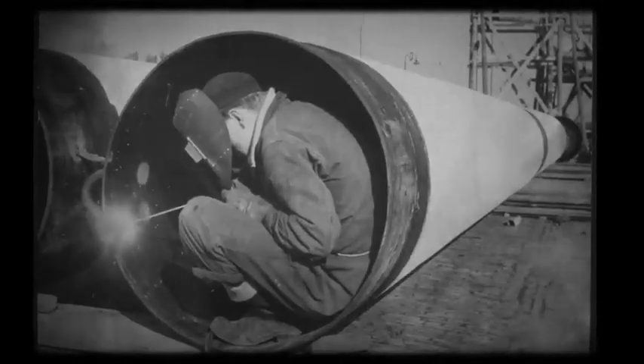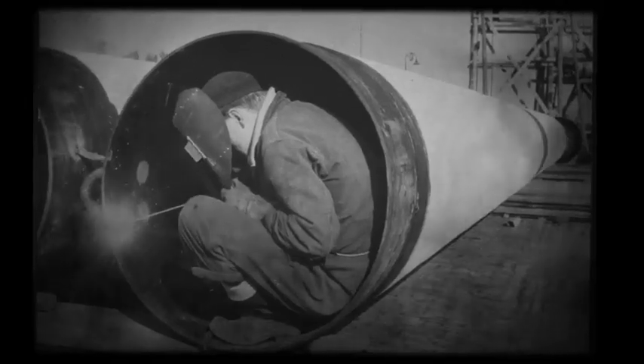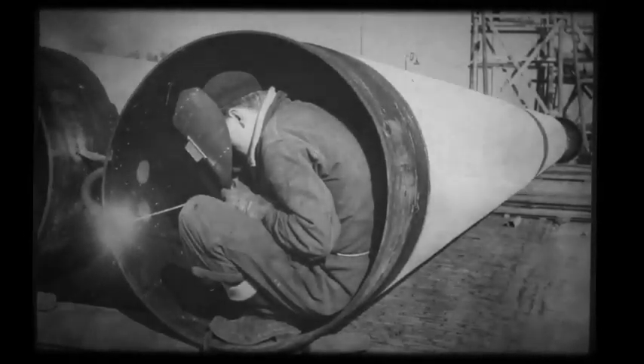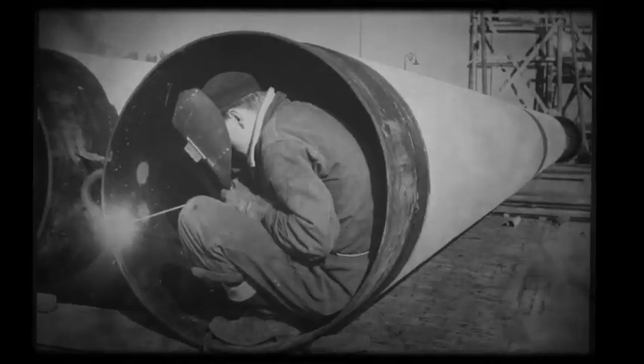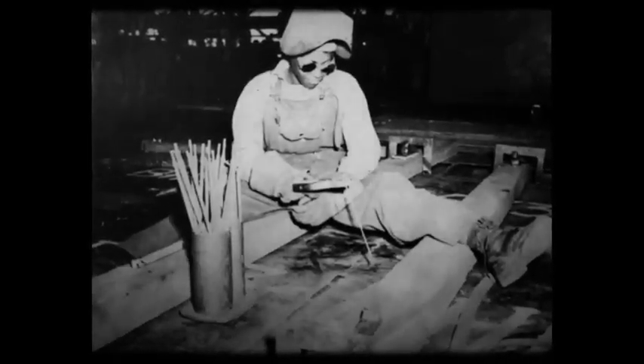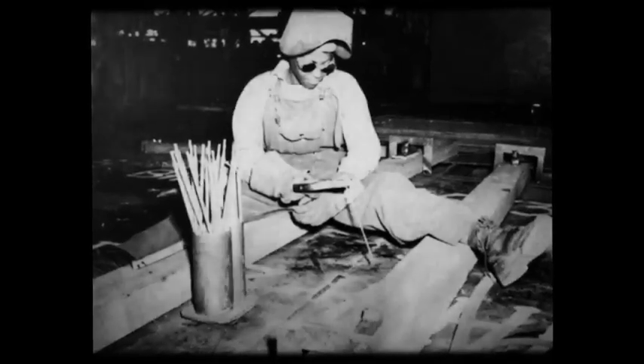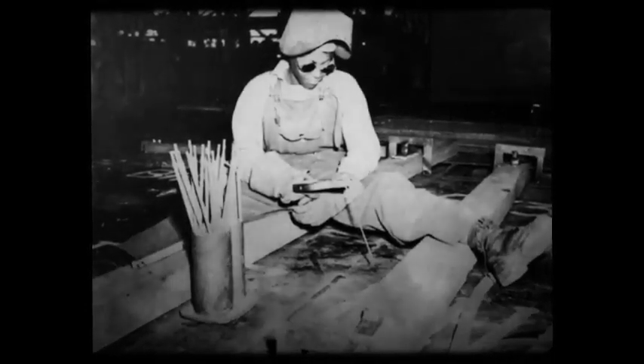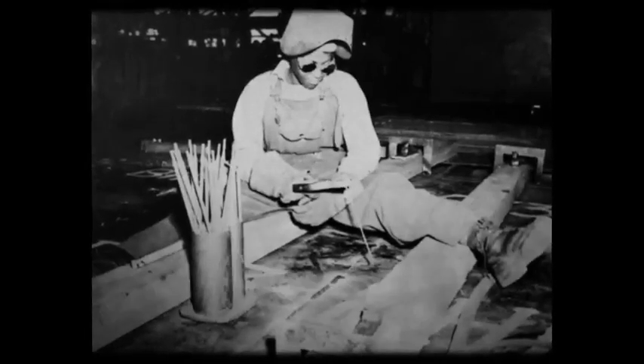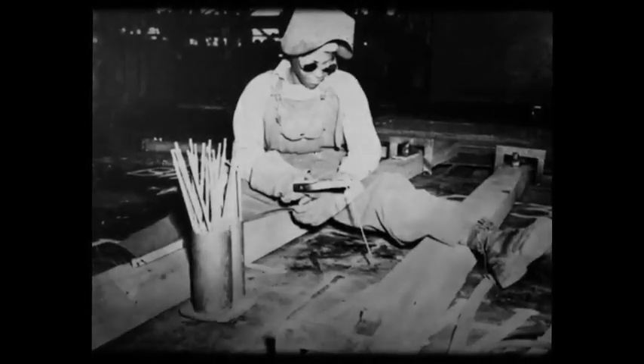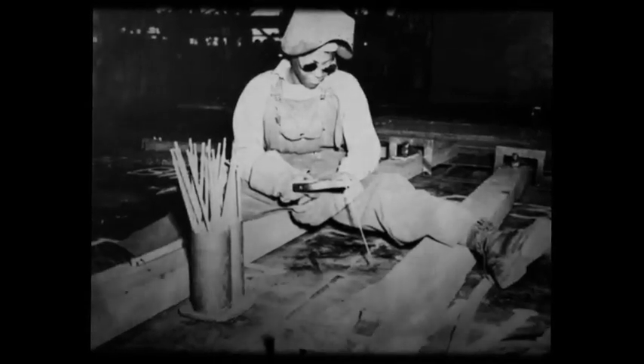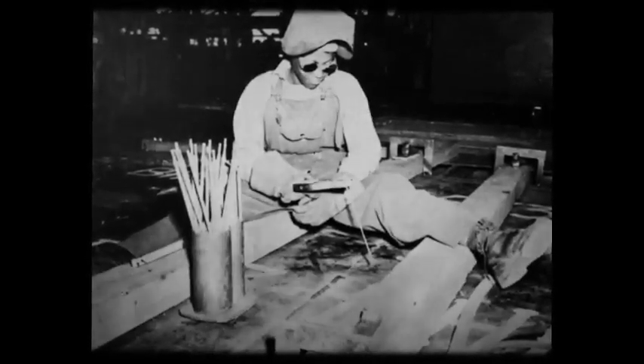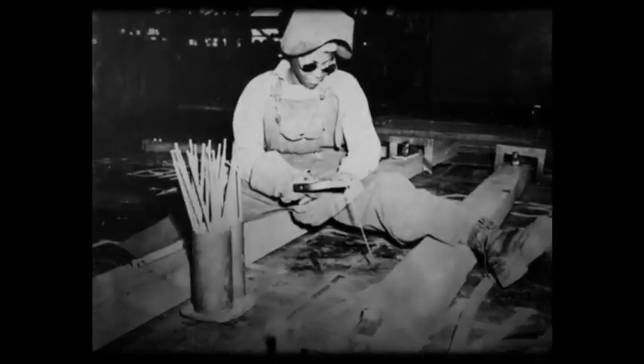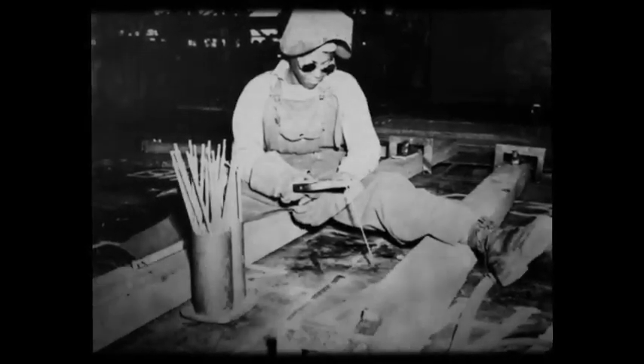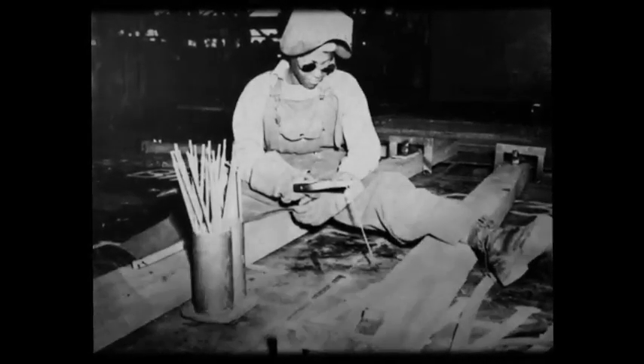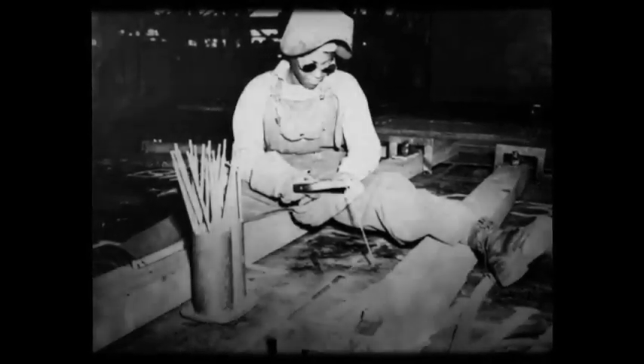Kaiser's engineers began studying from the breakpoints backward. Every square corner in the Liberty ship design was replaced with smooth, rounded curves. The hatch openings that had started so many cracks were redesigned with wide, gentle shapes that spread out the stress instead of focusing it into breaks. The deck and hull plate thicknesses were recalculated not to add more raw strength, but to make sure stress spread evenly with the new welding order. The structural frames were moved and realigned to match the new natural flow of stress. The new ship frames were now placed to line up with natural stress relief points instead of pushing against the welding pattern. The steel itself was also changed.